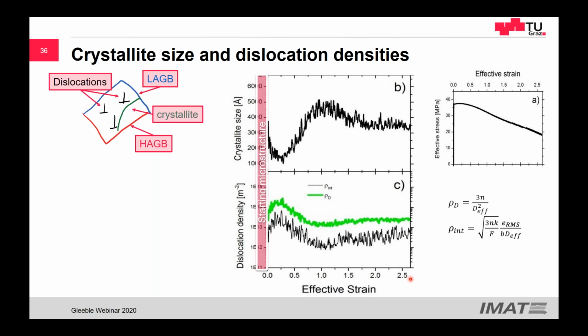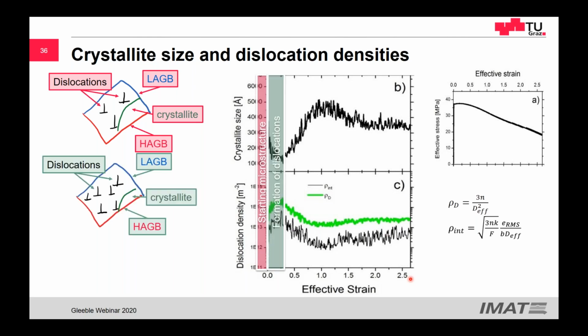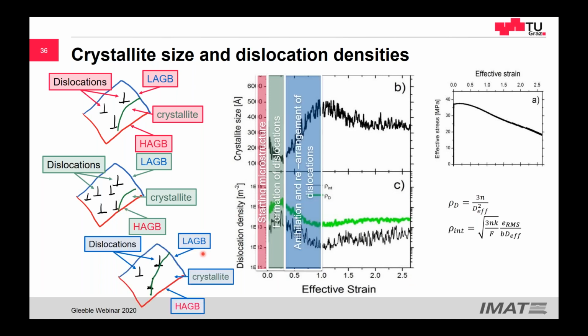And this is our understanding. So we have a starting microstructure that is forming dislocations and low angle grain boundaries. And then we form a lot of dislocations, breaking the crystallite size. So the crystallite size is smaller. And then we have a dynamic recovery, and therefore the dislocations are arranged into low angle grain boundaries and the crystallite size increases again. And then it reaches a steady state during continuous dynamic recrystallization.